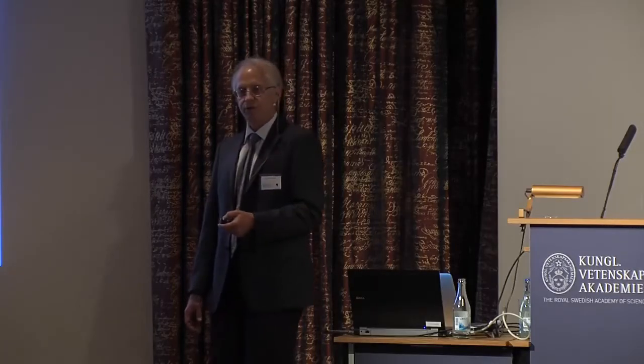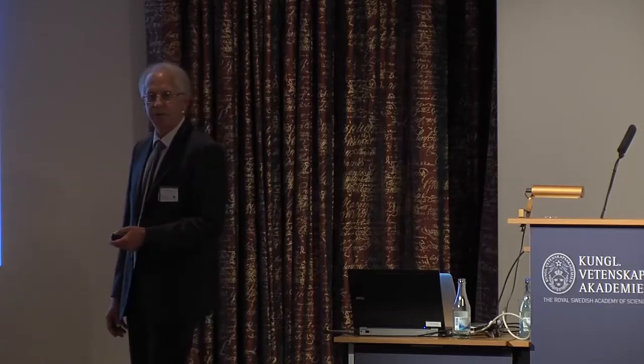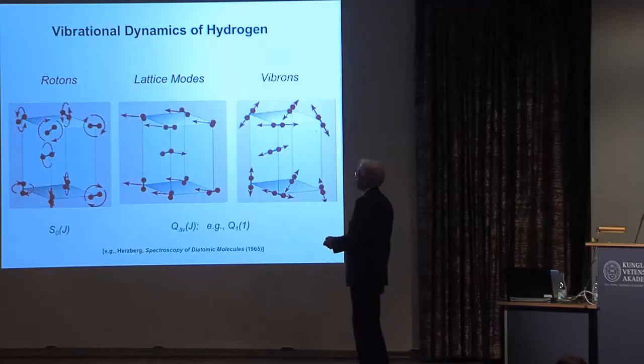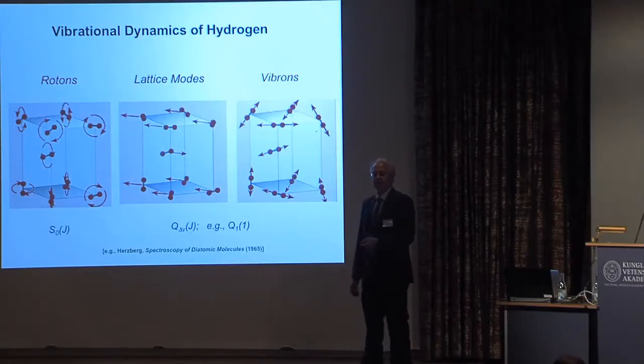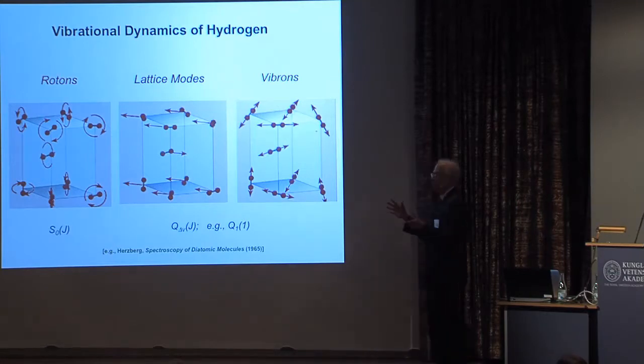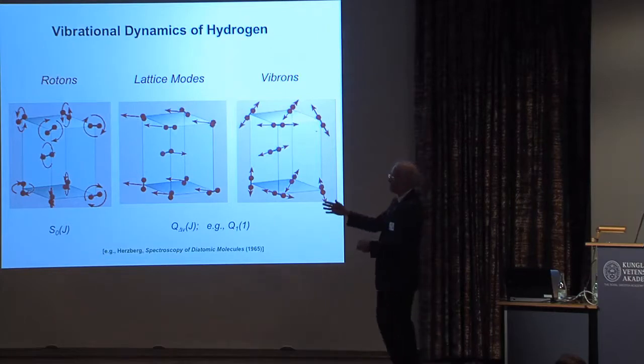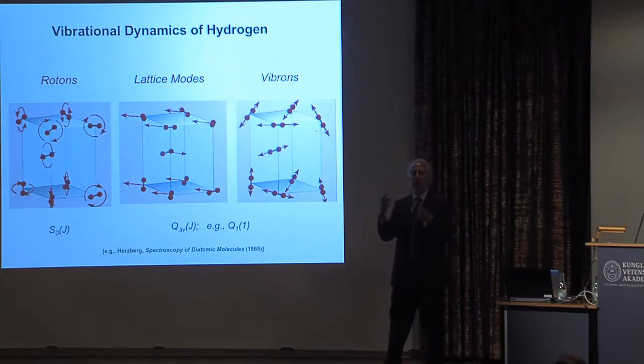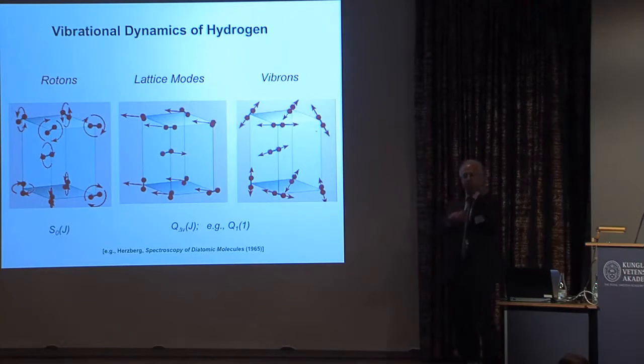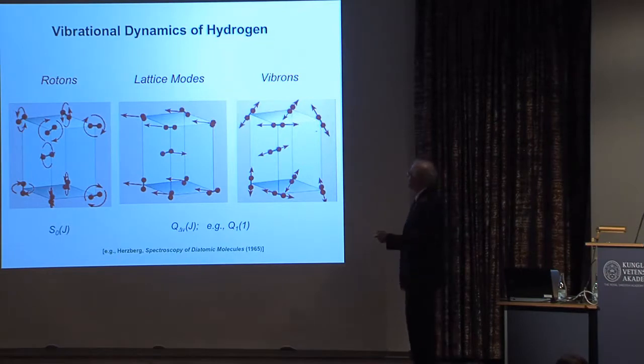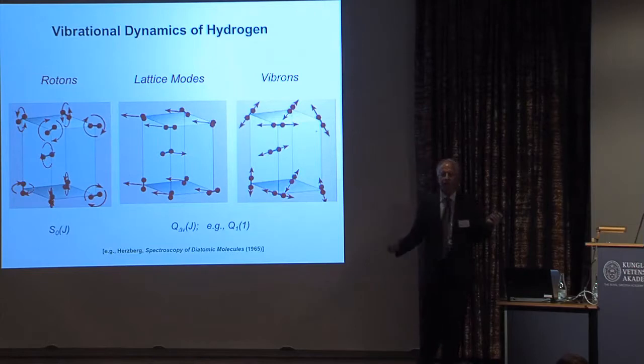And of these spectroscopic studies, vibrational spectroscopy has been particularly important. If one looks at the vibrational dynamics of this system, there are really three classes of excitations. There are the so-called rotons over here, which probe the rotational disorder, telling you whether you have the molecules ordered or not. You have the lattice modes, which are diagnostic of particular crystal structures. And then the so-called vibrons, which are the intramolecular stretching modes.